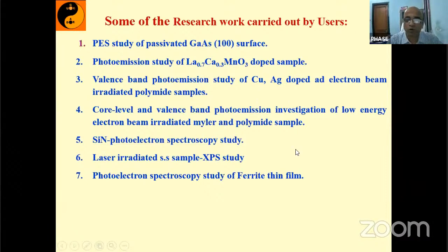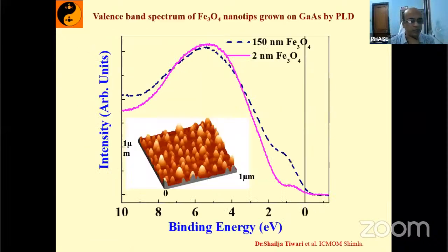Then core level and valence band photoemission investigation of very insulating samples you can also do, because in the laboratory insulating samples basically give noise. And because of that noise, you will not get a very good quality spectrum. But here, intensity-wise, it is very large, so one can get a good quality spectrum. Signal to noise ratio is also very high here. Then silicon nitride photoelectron spectroscopy, laser irradiated samples. Wherever surface physics is concerned, whether you are interested in surface properties, then you can go and do photoemission spectroscopy.